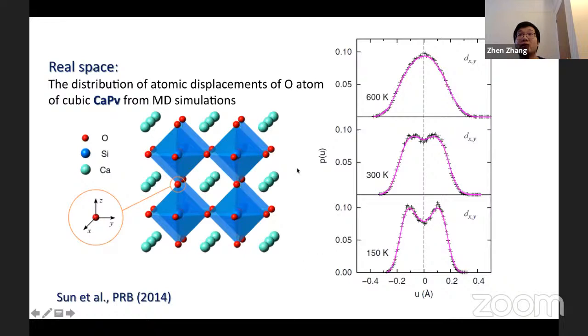The coupling between the dynamical stabilization of the cubic phase and the validity of the phonon quasi-particle picture was confirmed. Here in real space, the distributions of atomic displacements of oxygen atom with respect to the cubic phase equilibrium position from MD simulations are shown. At temperatures below 600 Kelvin, for example, 300 Kelvin and 150 Kelvin, the oxygen atom tends to deviate away from the cubic phase equilibrium position. This indicates the dynamical instability and distortion of the cubic phase. And an effective double well potential still exists at 300 Kelvin. However, at 600 Kelvin and temperatures above, the cubic phase is dynamically stabilized.